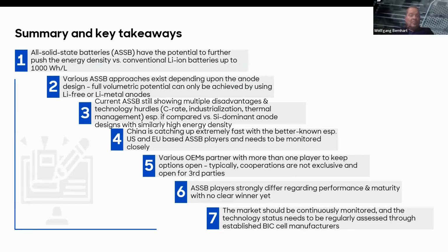So having said that, to summarize and give us hopefully a few minutes for Q&A, we do see all solid-state batteries that they have the potential to further push energy density versus conventional lithium-ion batteries up to 1,000 watt-hours per liter and 400 or more watt-hours per kilogram. There are various approaches, but the full potential can only be achieved by lithium-free or lithium metal anodes. So by getting rid of the anode material that consumes a lot of space. We do see multiple disadvantages and technology hurdles still, mainly around the C-rate, the industrialization challenges.